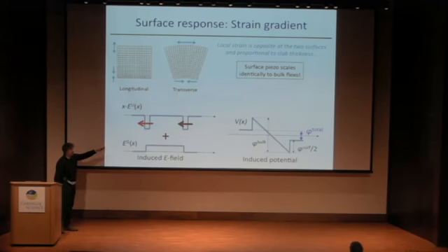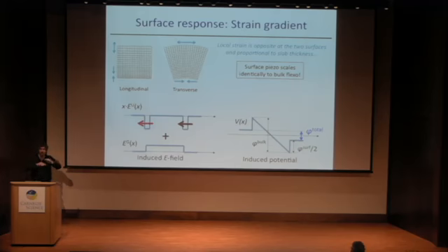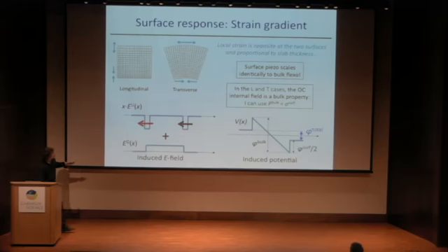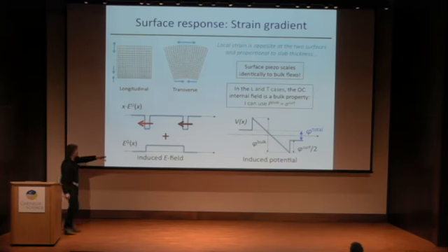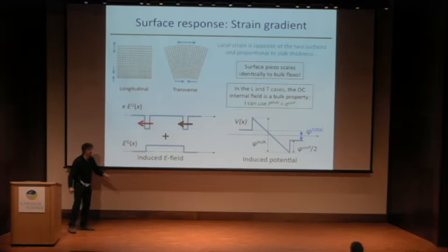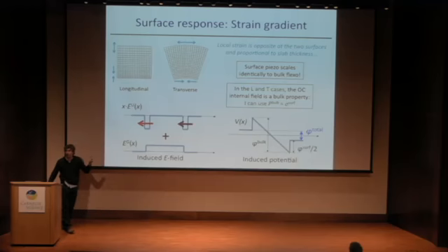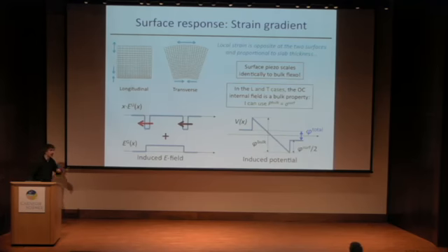So this means that if I take even a macroscopic surface, the overall response will be sensitive to what is the atomic nature of the terminating layer. And this also has a comforting message in that it says that the surface effects essentially concern only this region, which is close to the surface, while in the bulk, the internal field is indeed a bulk property. So I can use this technique that I showed you before to infer the bulk tensor from a slab calculation.